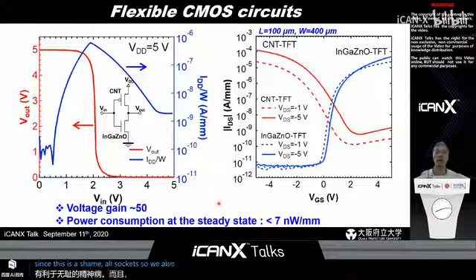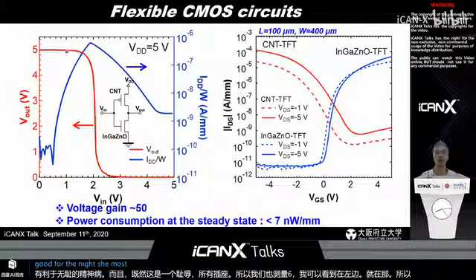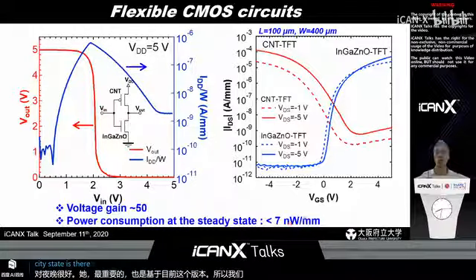And since this is a CMOS circuit, we also measured the inverter characteristics, as you can see on the left side. Based on that, the performance is good for the CMOS inverter, and based on the penetration current, we can extract the power consumption at the steady state, which is less than 7 nanowatt per millimeter, normalized with the channel width. The voltage gain of this CMOS is around 50.